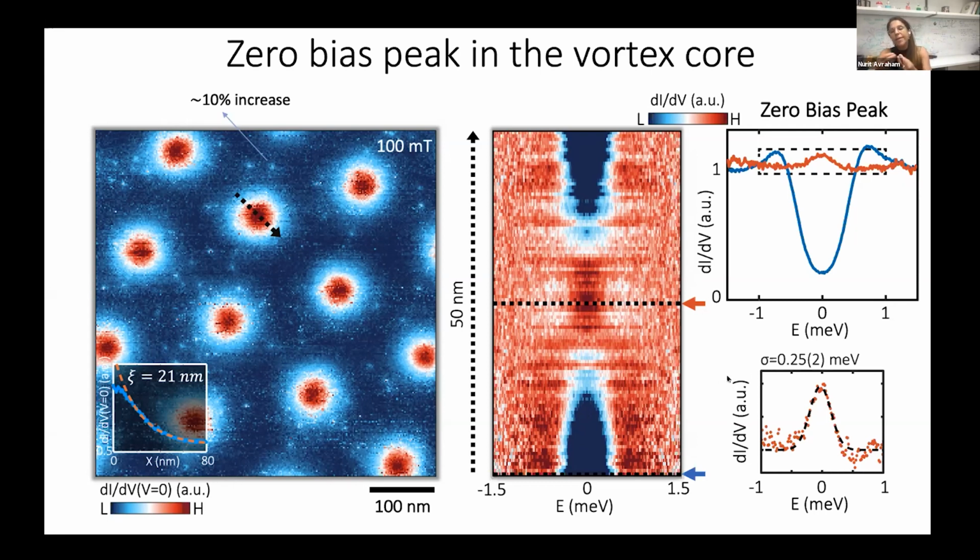But it turns out that this peak can also originate from a CdGM state, Caroli-de Gennes-Matricon state, and it turns out that the level spacing between these CdGM states doesn't allow us to distinguish, for example, the existence of a Majorana peak from the existence of these CdGM states.